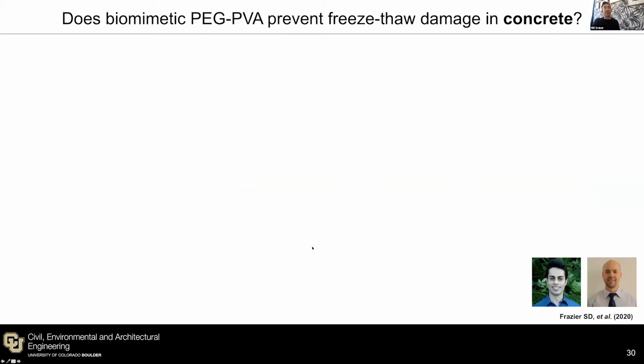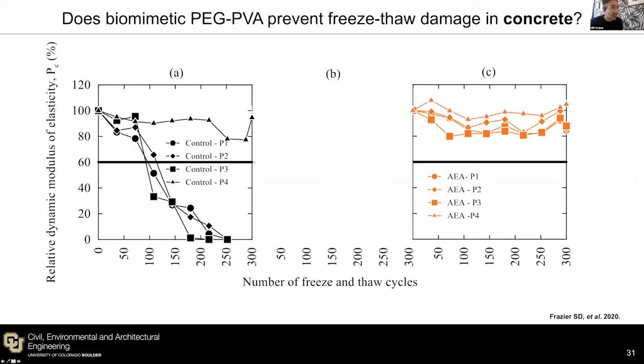So does biomimetic PEG-PVA prevent freeze-thaw damage in actual concrete? This is what Mo, my PhD student, and Shane also recently found the answer to. What you're looking at here is data from a freeze-thaw test of concrete. On the x-axis is the number of freezing and thawing cycles. We made samples of concrete and exposed them to freezing and thawing cycles up to 300. What we were measuring is the relative dynamic modulus of elasticity, which is essentially the integrity of the sample through the thickness, again comparing that to a pristine sample that didn't have any exposure to freezing and thawing. And what we found was that the control sample without any air entrainment or any molecules quickly failed after about 100 cycles, which is what we would expect.